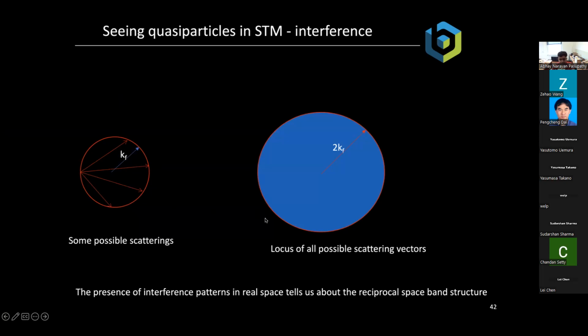And if I consider the locus of all these possible scattering vectors for this particular simple Fermi surface, which is a circle, the locus of all possible scattering vectors is also a circle, but with a wave vector that is twice the original wave vector of the Fermi surface. And the reason for this is simple. The maximum possible scattering wave vector is from one end of the Fermi surface to the other. That's the backscattering wave vector.